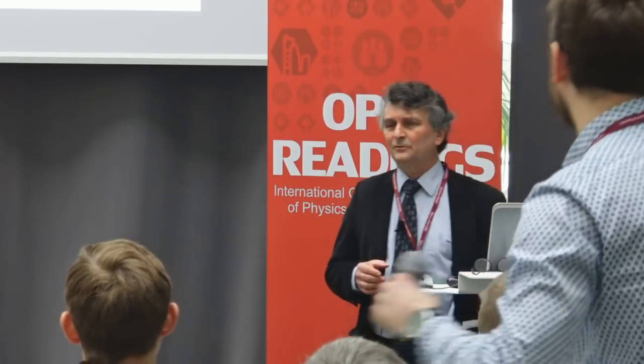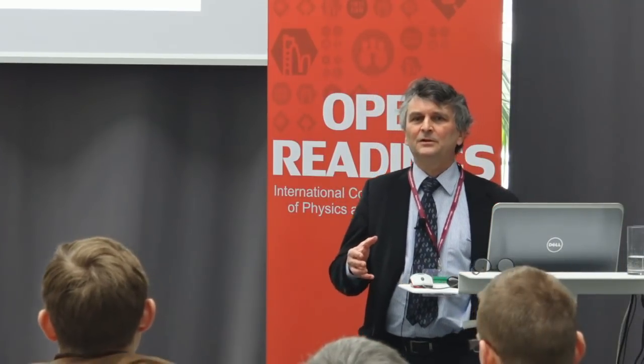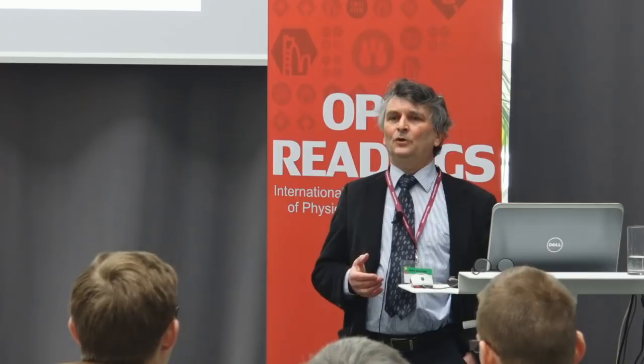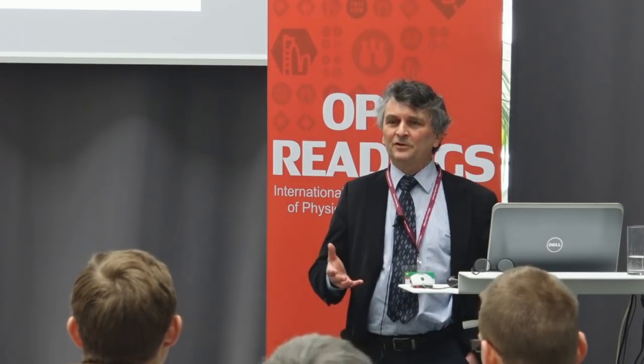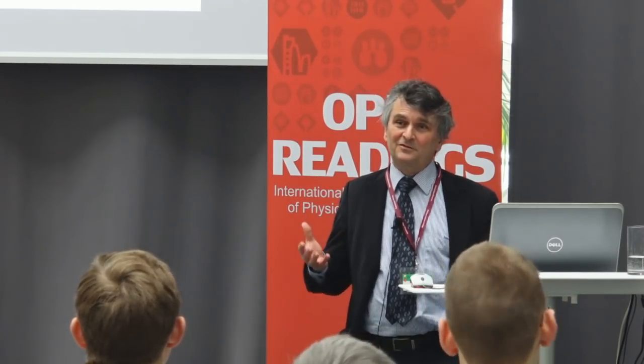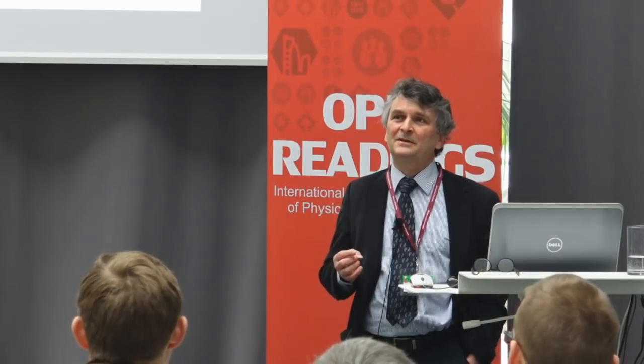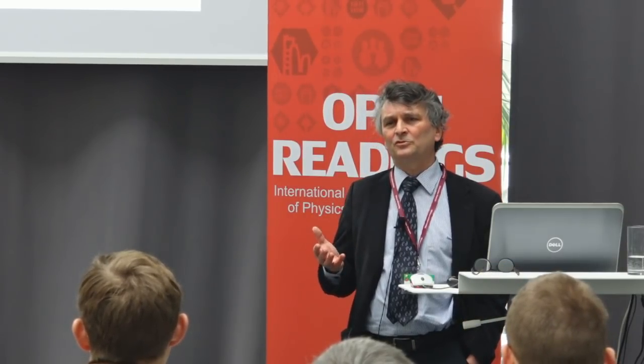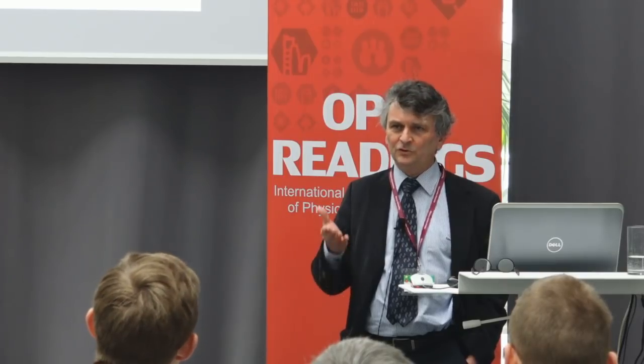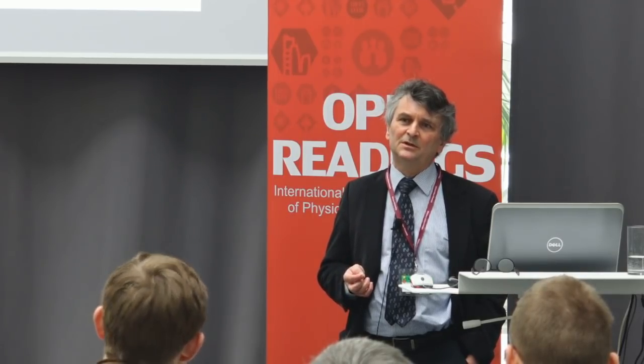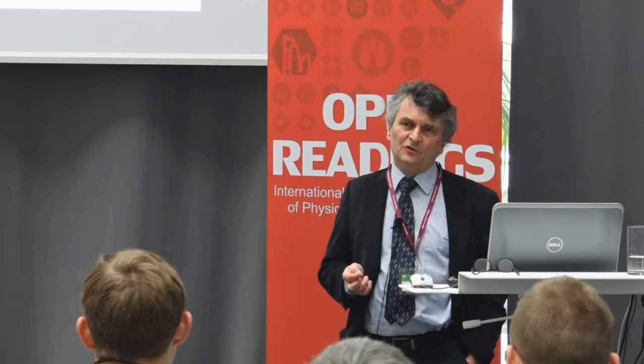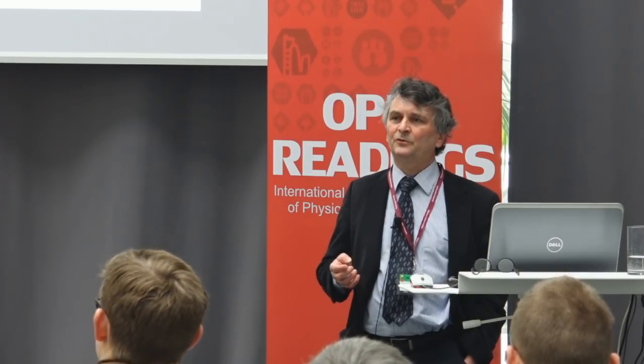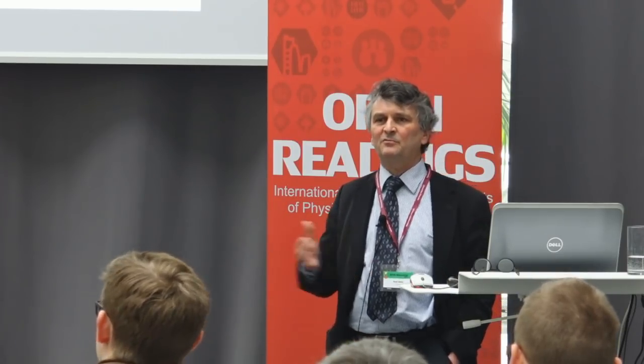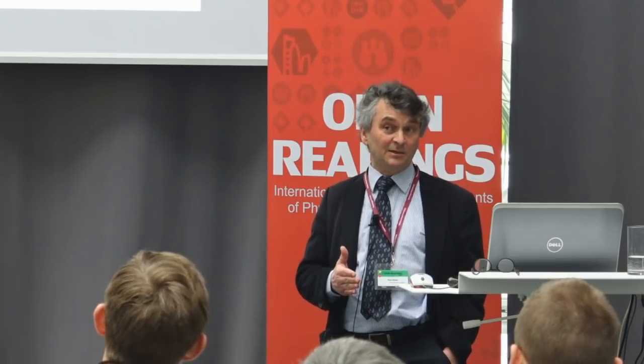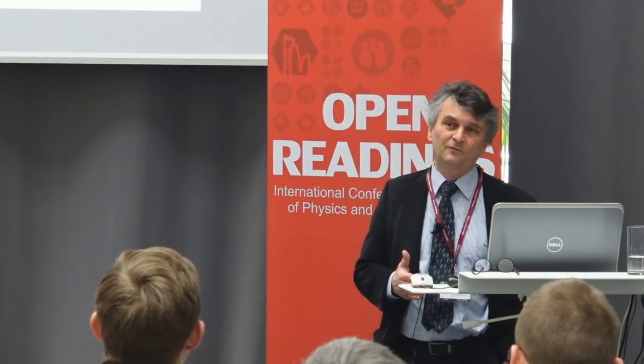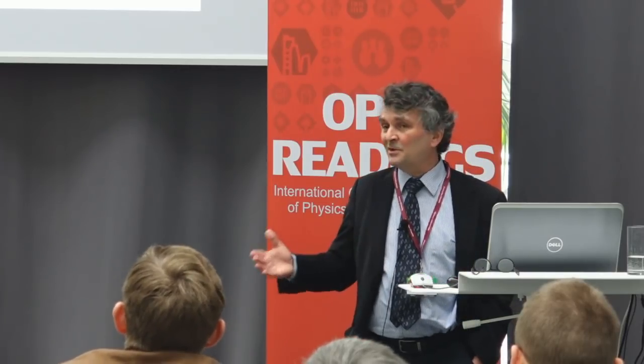Well, to come back first of all on the III-Vs on silicon, which has been a big field for obvious reasons for the past 20, 30 years, there have been some successes on growth of gallium arsenide on silicon, often through an intermediate of germanium. That has worked reasonably well, but of course, indium phosphide is more difficult. The lattice mismatch between indium phosphide and silicon is already 8%. Gallium arsenide to silicon is only 4%. So the lattice mismatch is the first problem.